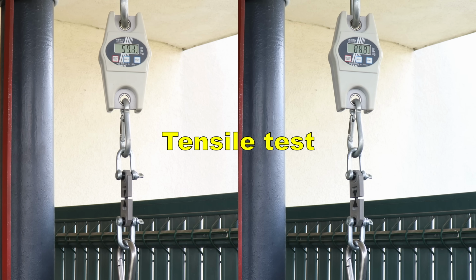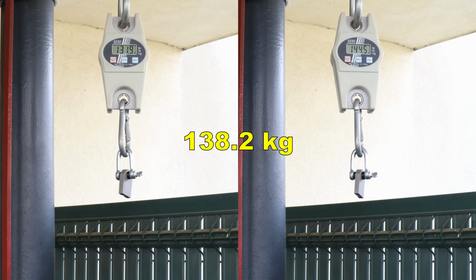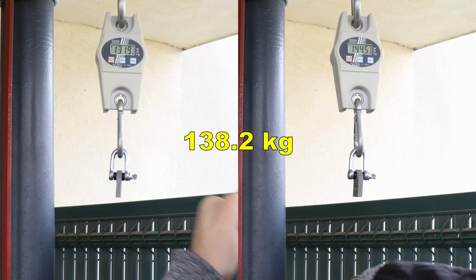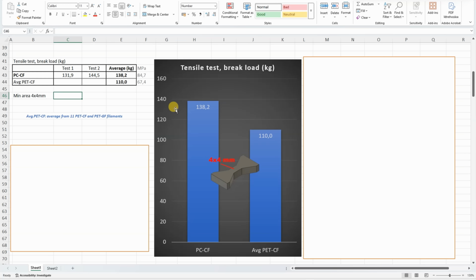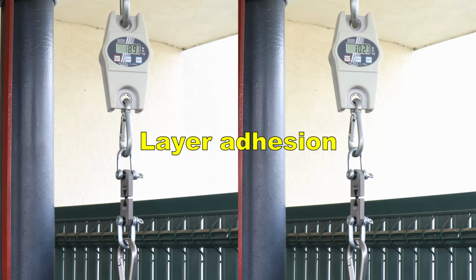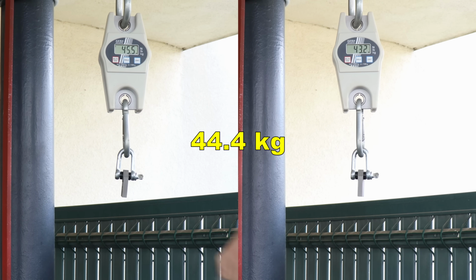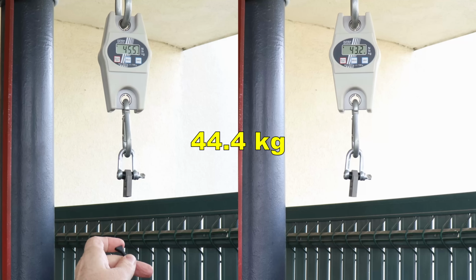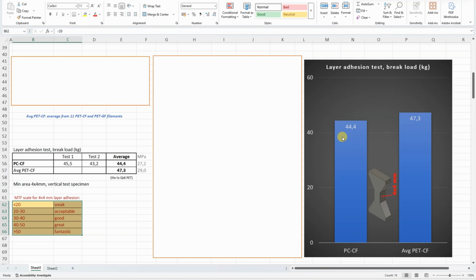Tensile test with horizontally printed objects. Quite strong. This is fantastic tensile strength, not only compared to the average PET-CF, but almost to any other filament type. Layer adhesion, vertically printed. This is good too. According to my rating, this is a great layer adhesion.